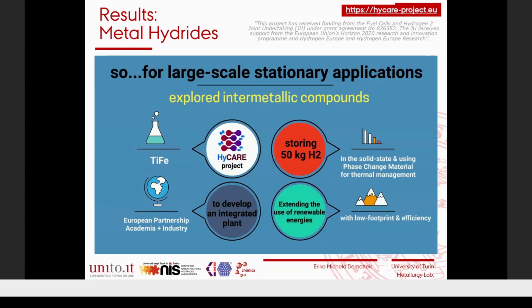And that's why we also moved our research to metal hydride, and in particular intermetallic compound, as for example titanium iron, that has been selected for the HyCare project. In the HyCare project, we have a European partnership, both academia and industry, that try to develop an integrated plant to store 50 kilograms of hydrogen in the solid state using iron titanium compound. And coupling this solid state storage with phase change material to improve the thermal management of the plant and also to improve the efficiency and have a low footprint of the entire system. And of course, extending the use of renewable energy by hydrogen.